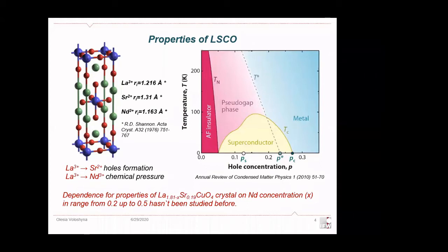And these superconductive properties appear when this plane is doped with charge carriers, for instance the holes that are formed with substitution of lanthanum with divalent strontium atoms. Additionally, we can substitute lanthanum in the lattice with a neodymium ion to create the so-called effect of chemical pressure that strongly influences the Tc value.